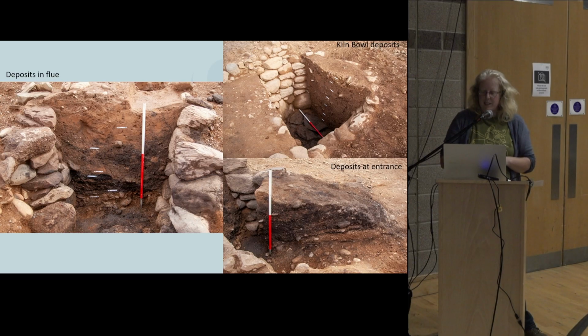Radiocarbon dating from various deposits indicates the kiln was likely constructed no earlier than the 14th century AD, and then in use from the early 14th to the mid-15th century AD. After it went out of use, the infill deposits show that it's been deliberately infilled in places, and these are quite different in the kiln bowl in contrast to the deposits in the flue where the fires were set, but both areas demonstrate multiple separate infilling events. The deposits on the bottom right show here the area outside the kiln flue, and they are largely related to rake and clear out events.